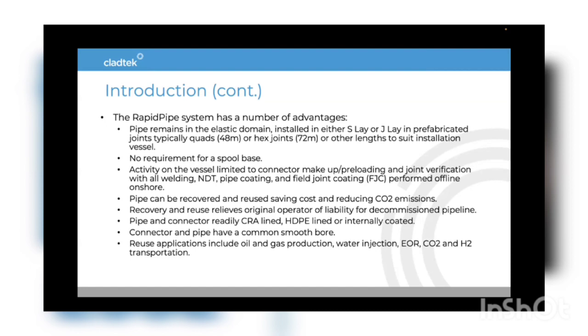So when we use a vessel of opportunity, like a large construction support vessel or a drilling rig, you have one station for makeup and a station for field joint coating. And if you compare that with welding, say CRA, where you have a station for beveling, a station for root and hot pass, NDT of the root and hot pass, potential cutouts or repairs of that for another station, fill and cap, more NDT, more potential cutouts and repairs. That's the reason why CRA is relatively low productivity.